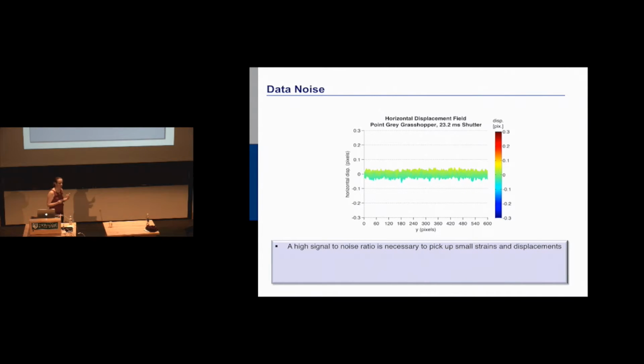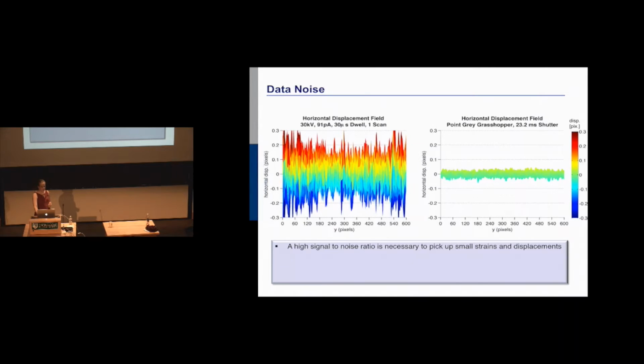There's also the fact that you have data noise in an SEM. There's inherent noise. When you take an image in the SEM, it looks very pretty, and you take a fly, you gold coat it, but you don't care as much about these really little noise issues. But when you're trying to get statistically significant measures of deformation, you do. This is a typical noise profile of an optical camera, a really high quality 5 megapixel optical camera. And this is a typical noise profile of an SEM that's been pretty well matched. These are reasonable settings that you would choose.